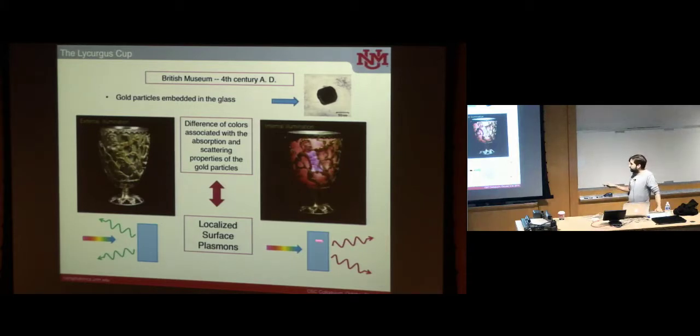And then, of course, you see the light that has not excited plasmons. So if you take away the green part of the spectrum, you are left with mostly red light. And of course, you also get rid of the blue, because even though you don't have plasmons excited in the blue, you always have interband transitions in the gold, which come from essentially bringing electrons from the D to the S band, and those produce absorption.